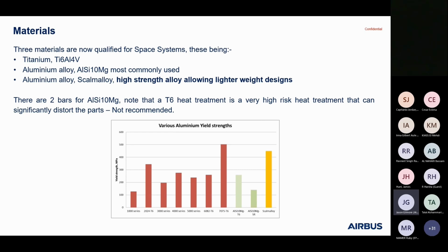So I mentioned T6 aluminium silicon 10. We qualified the T6 heat treatment on the TMTC bracket, and this gives you a yield strength around about 260 megapascals. And we kind of got away with it with the geometry of the TMTC bracket because there were lots of nice triangles supporting many of the beams. We then tried to heat treat other components that are a bit more spindly and less well supported, although they're fit for purpose in terms of the design and the stresses. And we had some significant distortion, so we went around a few loops of trying to correct that.